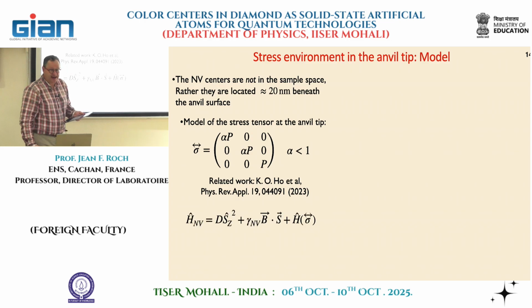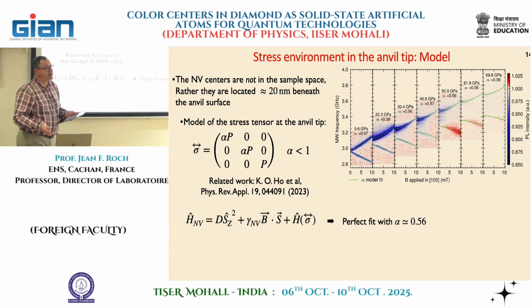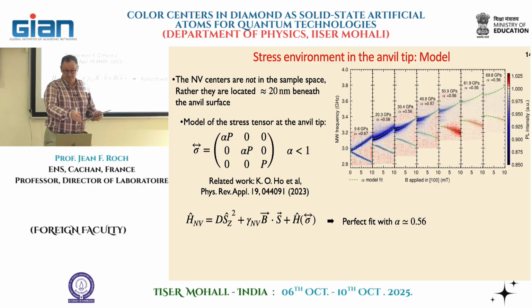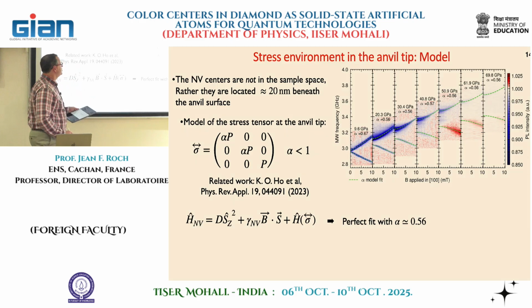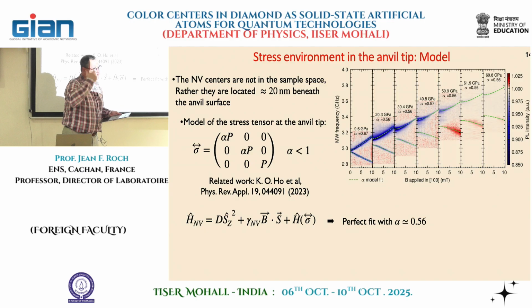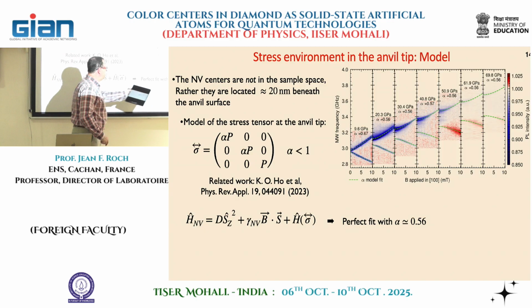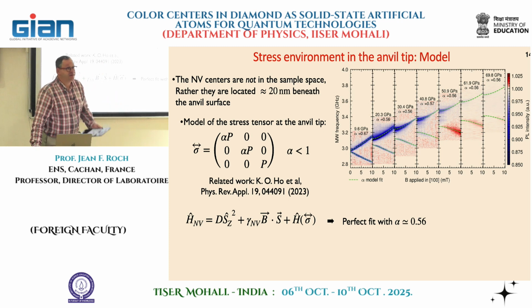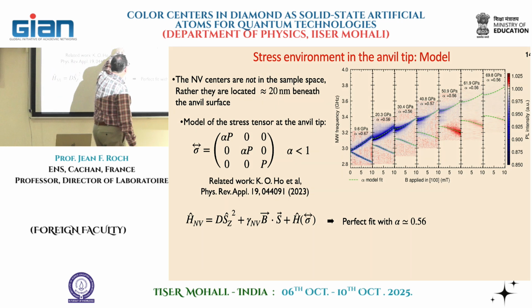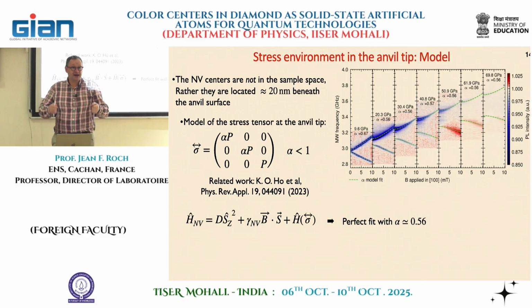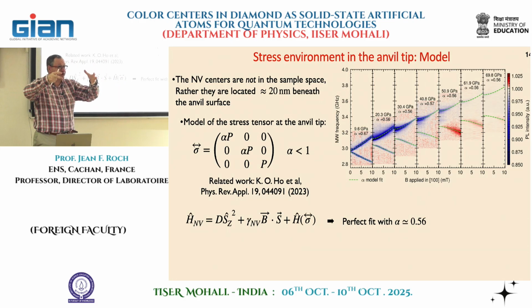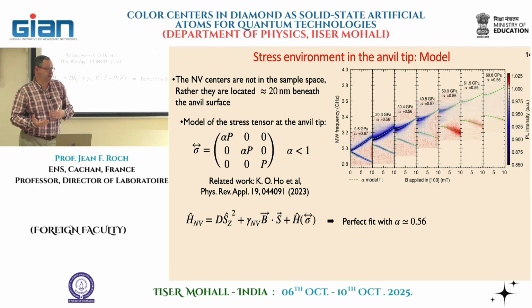We integrate that into the Hamiltonian, and once we have that, we can measure the Zeeman dependence as a function of this model. We clearly see positions of the resonances in very good agreement with this model, with an alpha parameter of around 0.6. And you see two effects. First, the mean frequency is going up. This can be understood very simply. I have the two electrons of the NV. When I apply pressure, they get closer and closer. So I strengthen the magnetic dipole-dipole interaction between the two electrons, which leads to an increase of the D parameter.